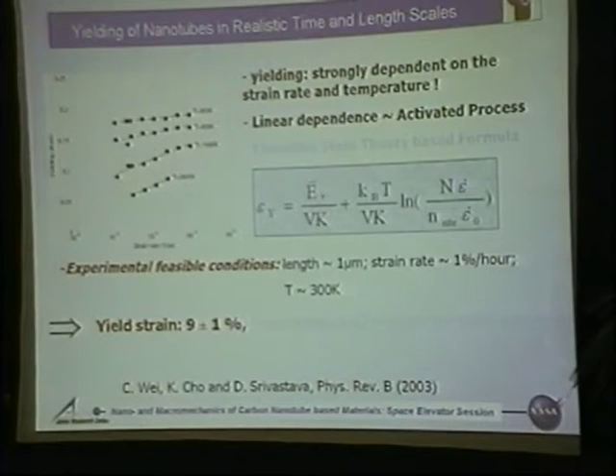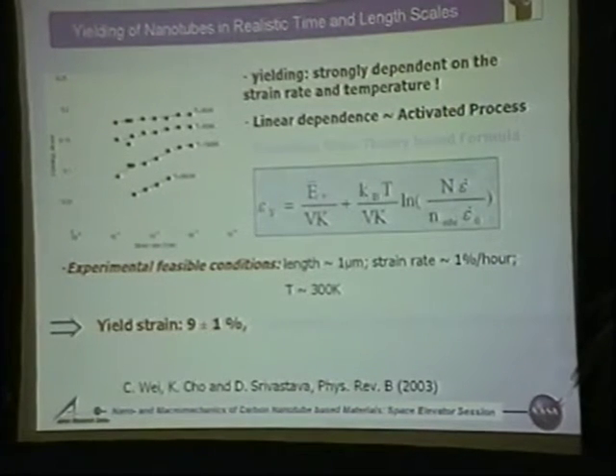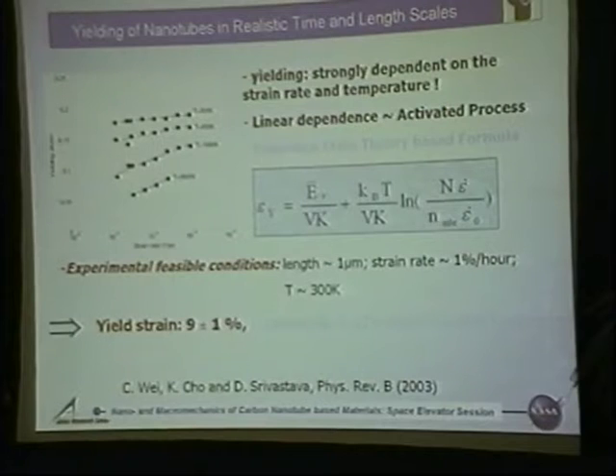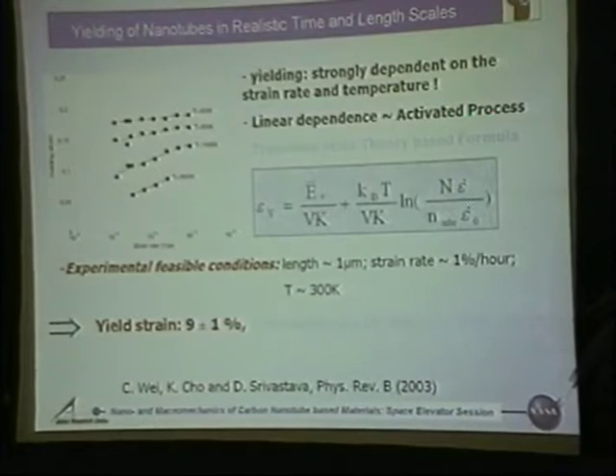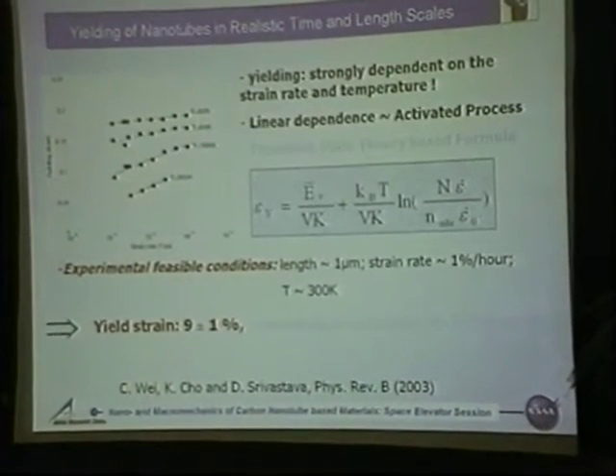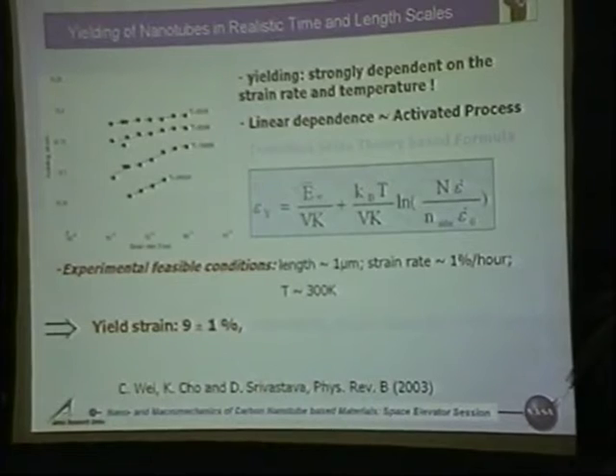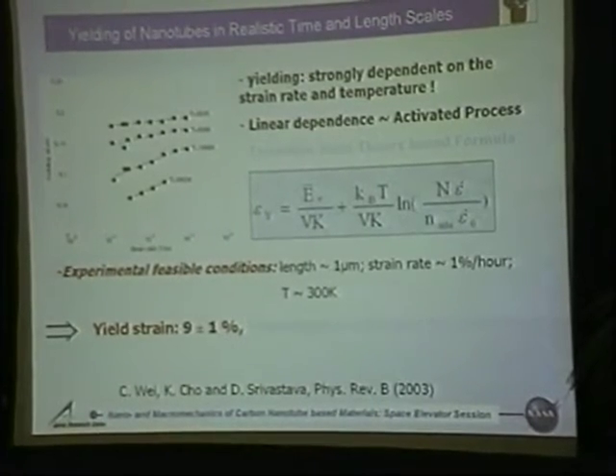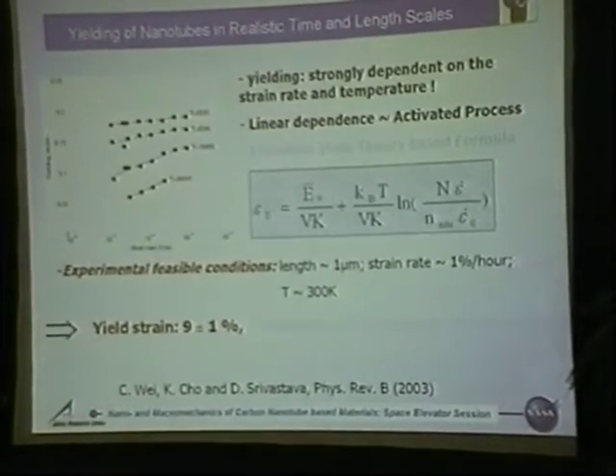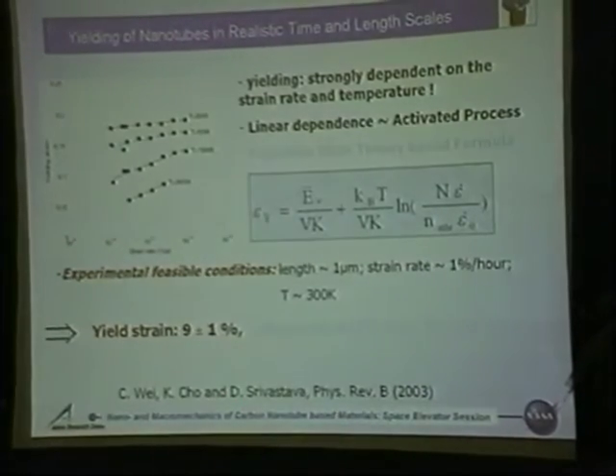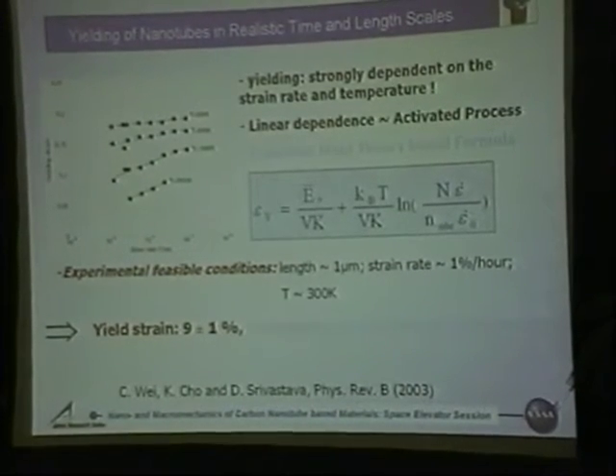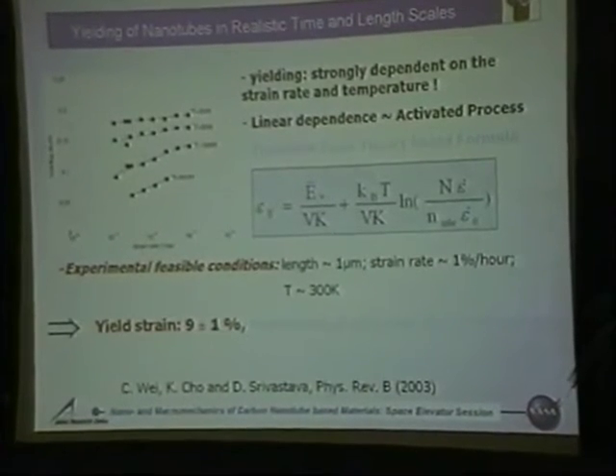So typically, if your modulus is about 1 terapascal, and you take 9%, let's say 10%, that gives you some kind of magic number, 100 gigapascal. And single wall nanotube density is 1.3 or something like that. So it does satisfy in that sense. I was not aware of it, but as those numbers started to come in, that probably got Brad and other people in the space elevator community enthusiastic about a material like nanotube. So this is single wall nanotube.